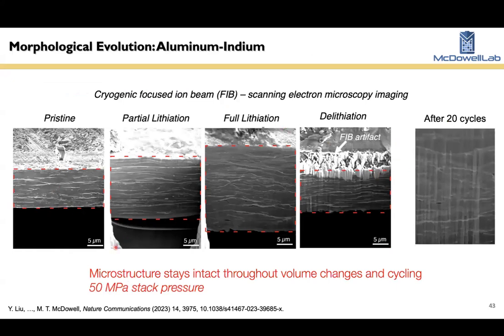So this is a view of the microstructural evolution of these materials. This is the pristine layered material. After you lithiate, there's this big expansion of the foil because you've inserted a lot of lithium. And the important thing here is that the microstructure still remains intact. You see the layered phase, the lithium indium phase is still there. When we delithiate, we have contraction again, and the microstructure is still intact. So the persistence of this microstructure, we think, is important for cycling.